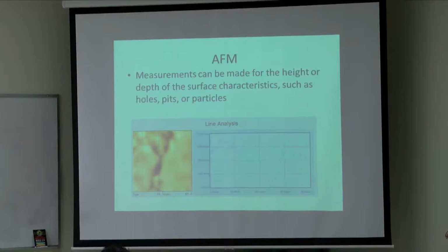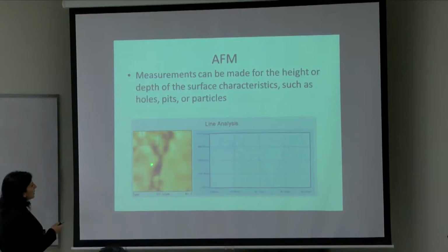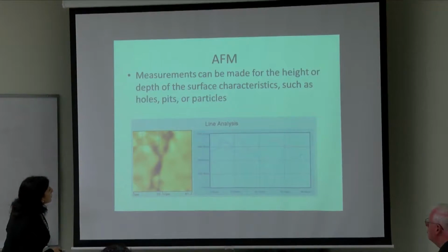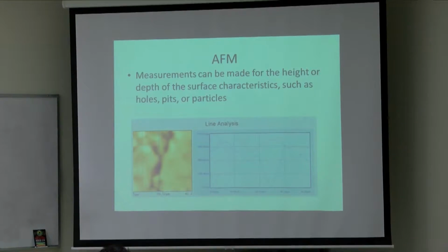So you can even do measurements with the AFM. So you can actually scan across and do a line analysis, and this will give you a graph to show you the actual quantities of the material. So for example, this dip here looks to me the lowest point of the sample in this screen, and this is what is used as the 0 mark, and the highest point is approximately going to be about, I don't know, roughly 1,000-ish. 1,000 nanometers. So that's the highest point. So that's about the thickness of the surface here.